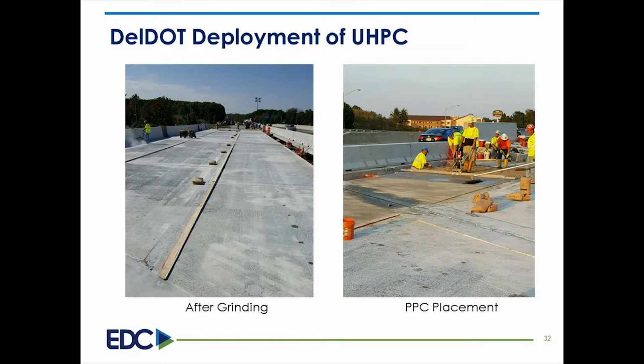And this was the final surface after grinding. And then on the right, you can see we're putting down the PPC overlay. It's like a light brown, very thin overlay on top of it to help take up for any of the differences.